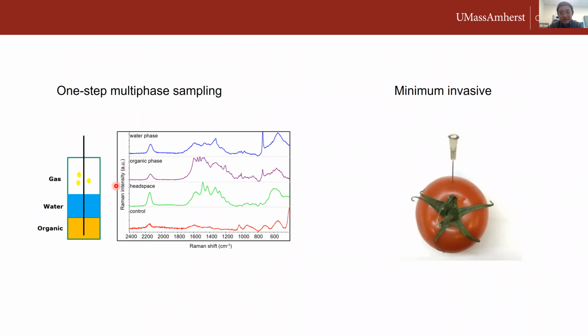Another example is the minimally invasive method combining SERS fiber and a needle. In this case, the needle is working as a shell to protect the SERS fiber. And this needle can be injected into the sample and then gradually removed from the sample, leaving the SERS fiber inside of the sample. As we can see here, this fiber is capable of collecting information in 3 phases. The organic phase, water phase, and gas phase all have their significant peaks, and they can collect useful information from the 3 phases.